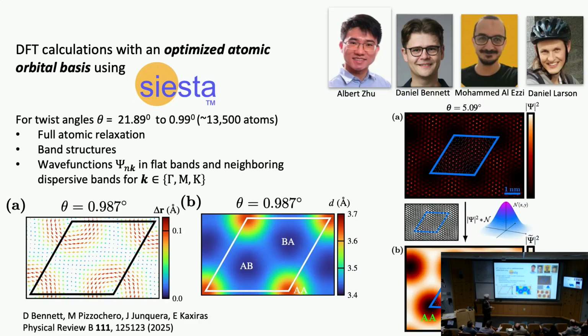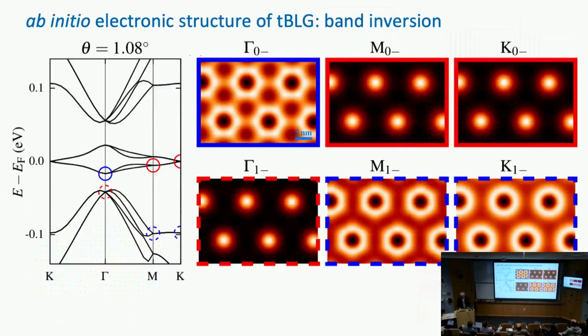So now I'm going to go to much smaller angles, all the way to 0.99 degrees, 0.987 degrees, which has much, much larger Moiré cells and many, many more atoms per unit cell. So you can't see all these details, but you can still see the interesting features of the wave function. So here's now 1.08 degrees. By the way, this choice of the twist angle was made because it's very close to the experimentally observed magic angle, where the flat bands and superconductivity happens and so on.